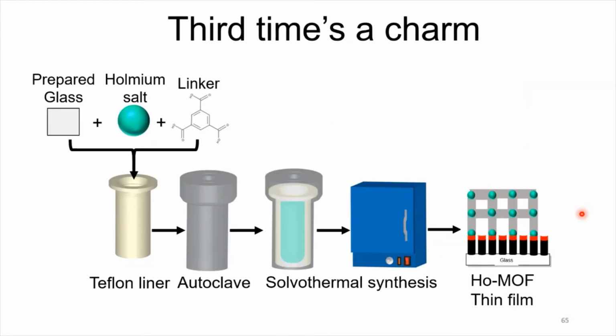And synthesis conditions are really not that far from what we've seen before. The 3rd time's a charm. Just instead of magnetite, we will go in and put the prepared glass slide, prepared by any of the methods that I mentioned before. Use your holmium salt and your linker. Here, we actually haven't seen any change in the synthesis results. As I mentioned, magnetite did require some modifications on our reaction times, but as long as we have seen on the glass, I think we actually have to adjust the time the glass needs to be in there to just have a thin film. Because if you leave the glass longer, of course you end up with big crystals on top of the glass, and that's not what you want.